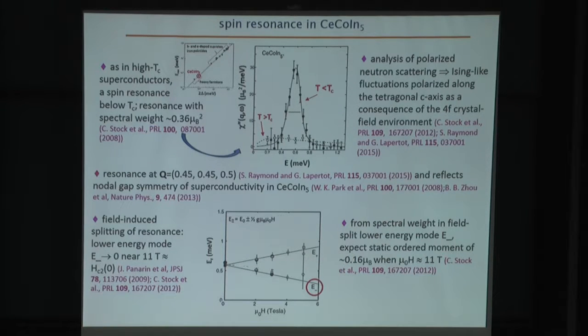So cerium-cobalt-indium-5, as I said, is a superconductor. And when we cool cerium-cobalt-indium-5 below a superconducting transition temperature of about 2 degrees, a very clear spin resonance develops in the superconducting state. And that's shown in this plot of the dynamic susceptibility as a function of energy, where we see this well-defined peak in the dynamic susceptibility that's centered at an energy of about 0.6 millielectron volts.